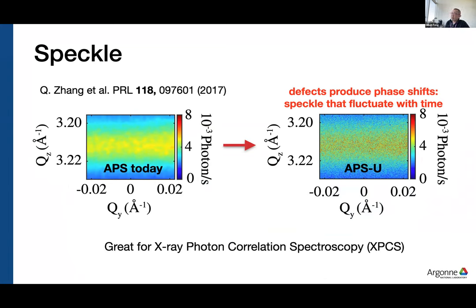So I'm showing a reciprocal space map that you can get today from the APS. It's on the left. And I'm showing the same reciprocal space map that you can get after the upgrade. And I'm showing you what speckle is. It's basically little pixelated areas on your area detector. And these speckles come from defects in your material. And when you're scattering with coherent X-rays, the defects produce phase shifts. And at any finite temperature, these phase shifts will move with time. And so you can get fluctuation information about your defects. And so that's what I think of when I think about XPCS.